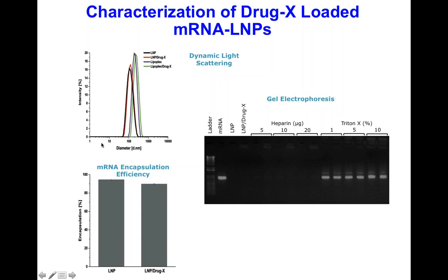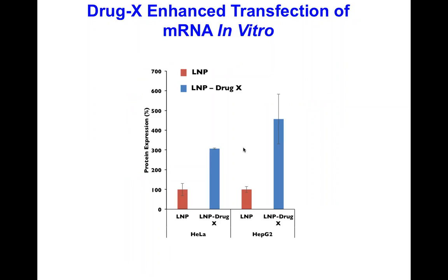And so we were able to quantify if there were any changes in the physicochemical properties in terms of the size, and we don't find much change in terms of the encapsulation efficiency. We are pretty good at encapsulating with or without the drug. In the presence of Triton to break apart these particles, we see a very similar effect with both the particles and particles with the drug. So we are able to formulate these bioactive lipids with the RNA.